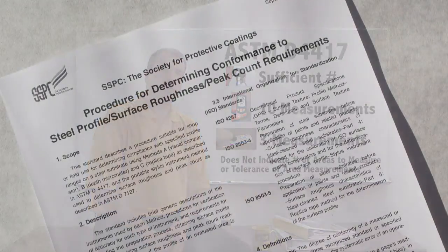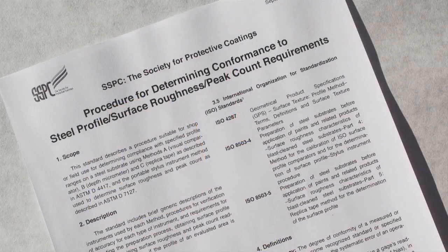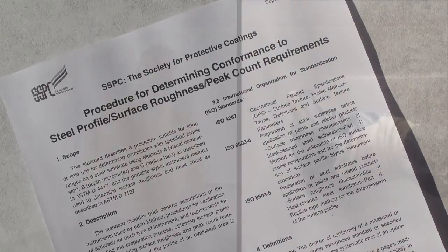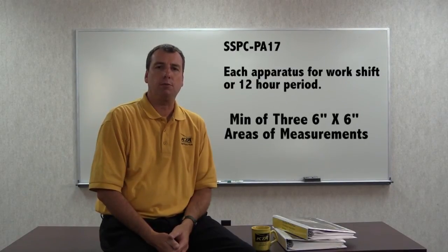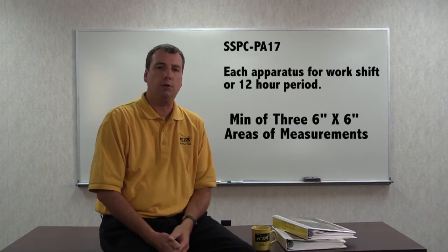As a result, SSPC published PA17, which describes a procedure for determining compliance with the specified profile ranges on a steel substrate in any of these three methods described by ASTM D4417. SSPC PA17 sets requirements for evaluating the preparation process, obtaining surface profile readings, and determining if the profile of an evaluated area is within the specified range. For each specific surface preparation apparatus used during each work shift or 12-hour period, whichever is shorter, you are required to select a minimum of 3 6-inch by 6-inch locations in which to take readings.